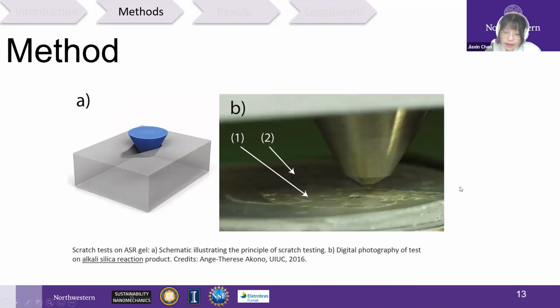As we can see, the diamond Rockwell stylus was pushing the surface of the materials. The right-hand side is a stylus scratching on our ASR prepared specimen. All tests were conducted using an Anton Paar micro-scratch tester, as shown here. In particular, the microscope and the scratch testing unit are synchronized so that we can select the location of the test with high accuracy and get an image of the surface after testing.